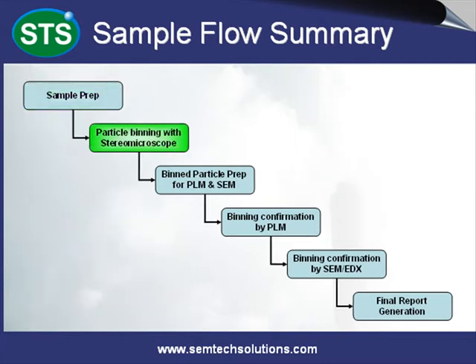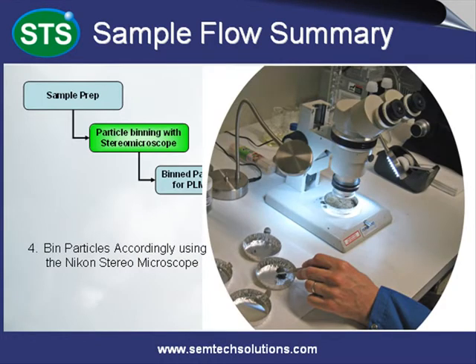After the sample is dried, the aluminum dish is placed under the stereomicroscope for particle binning. Preliminary inspection is then performed to detect and isolate any suspect particles with tweezers. Each suspect particle class is placed into its own separately labeled aluminum dish. As a side note, fly ash and oil soot are usually too fine to visualize with a stereo microscope and require confirmation by PLM and SEM analysis.